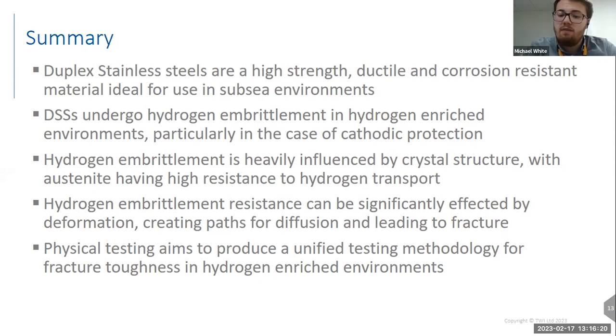Hydrogen embrittlement is heavily influenced by crystal structure, with austenite having high resistance to hydrogen transport due to its closely packed structure. This high resistance can, however, be influenced by deformation, altering the crystal structure and creating voids for hydrogen diffusion leading to fracture. The ultimate aim of this project is to produce an effective and accurate methodology for testing fracture toughness in duplex stainless steels, as many of the methods currently available for testing fracture toughness do not create an accurate enough result to be used within industrial applications.